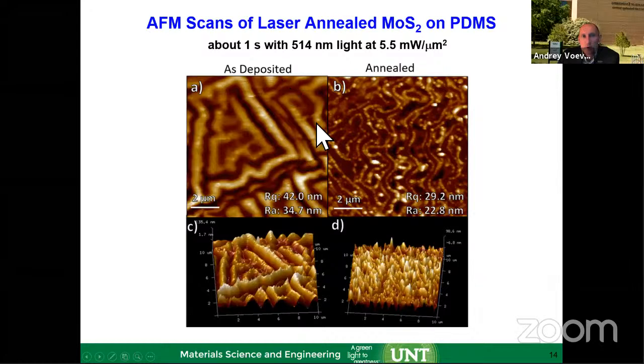So in terms of growth, when you're growing on a flexible polymer PDMS structure, which is a stretchable polymer, after you grow that and take it out of the vacuum chamber, the polymer shrinks, because in vacuum it expands, and once you get out of the vacuum, it shrinks. So it shows the corrugated structures in here, the surface of the film on the polymer getting shrunk. At first we thought, okay, could be a problem. But then we found it's not a problem at all, because we're talking about just a few monolayers of the semiconducting film, and because it's conformal and flexible, it just covers this perfectly. And in fact, after being shrunk, you can also stretch it. You can have a very high degree of stretching of that polymer and it is still operational.